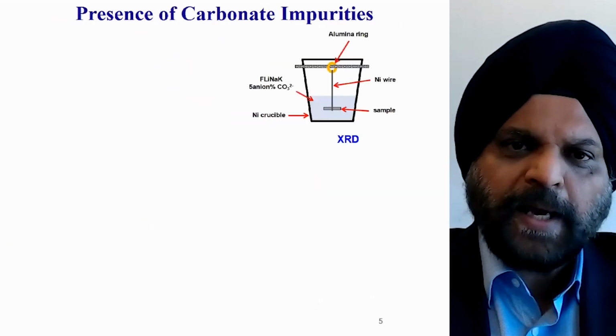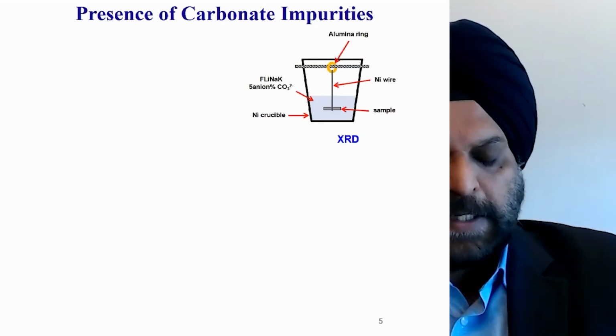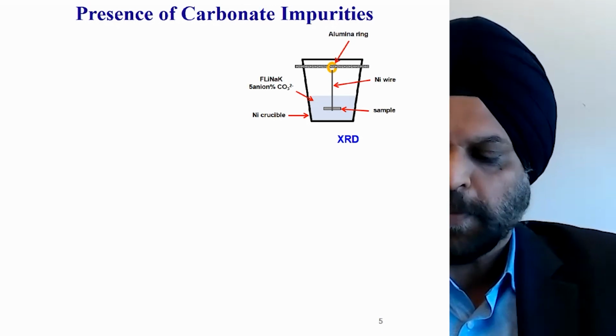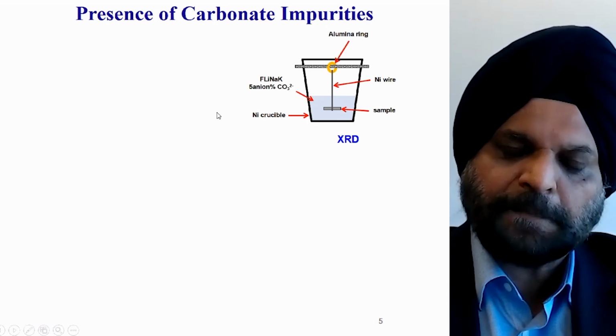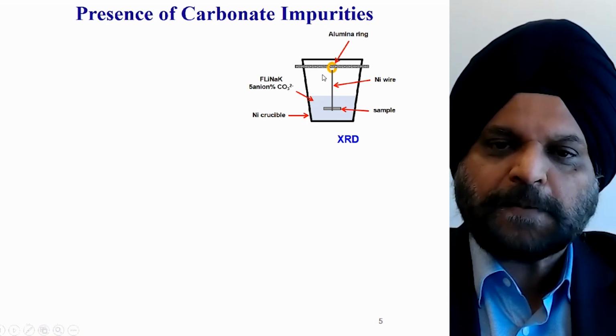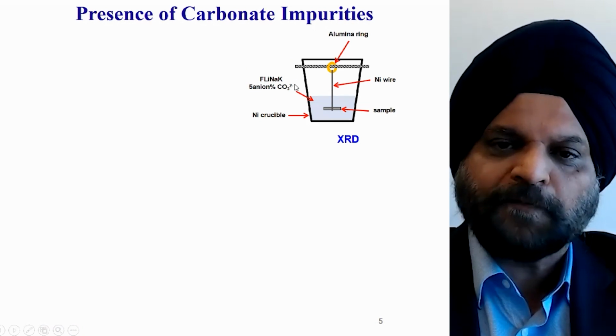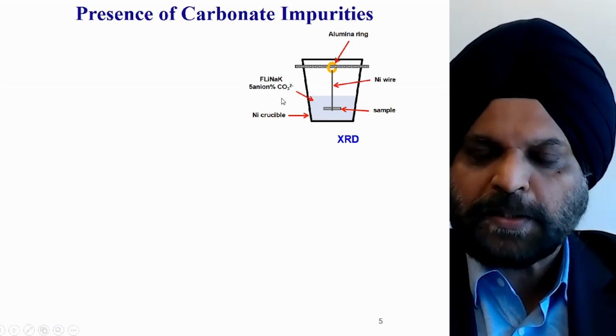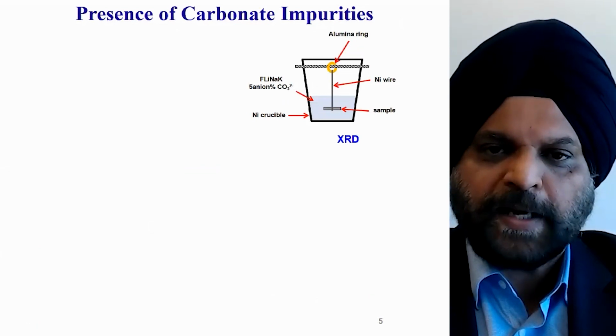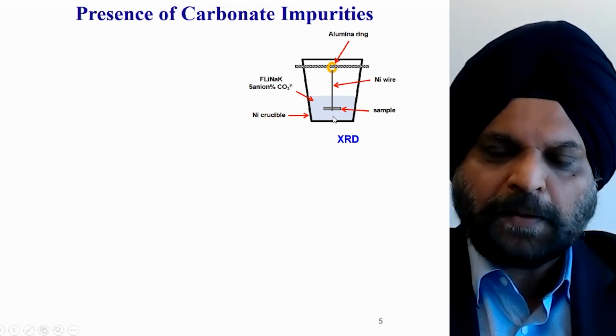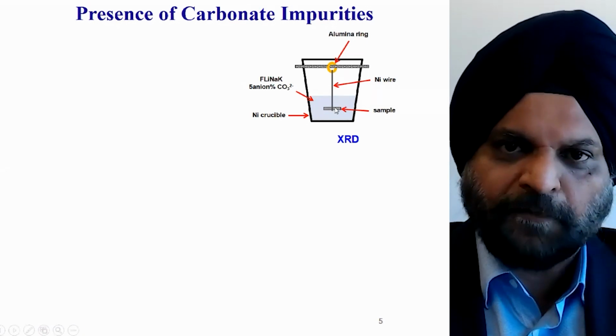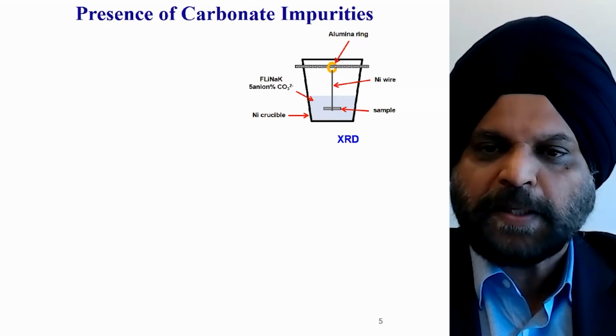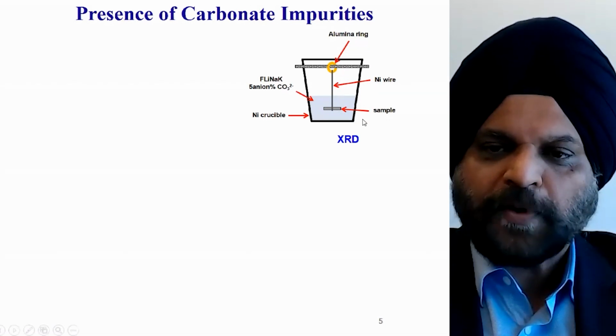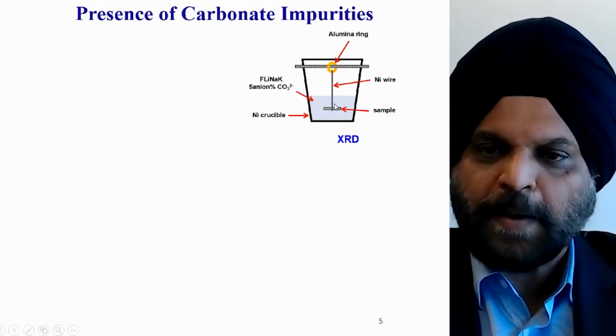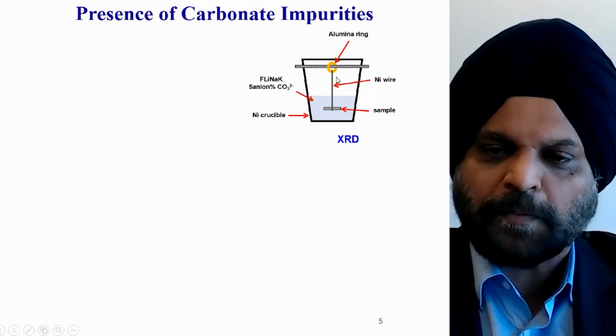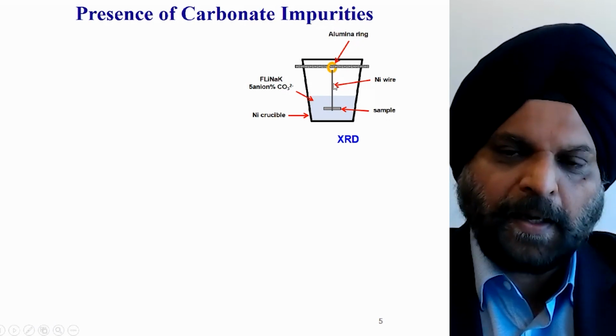Another impurity that we looked at was carbonate. Some salts do have carbonate impurities, but carbonates can also form by other means. In this set of experiments, FLiNaK was doped with different amounts of carbonate ions; basically, lithium carbonate was added to FLiNaK. This metal sample could be different metals, pure metals as well as alloys. Apart from carbonate, there is no other source of carbon. The crucible is nickel, and the sample is isolated from the crucible because it's hanging from an alumina ring.